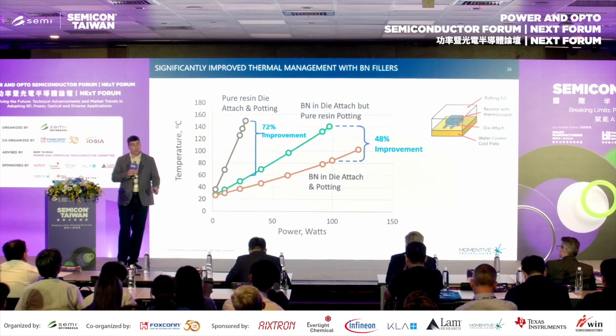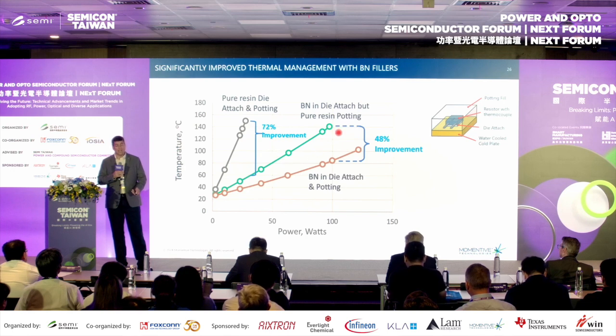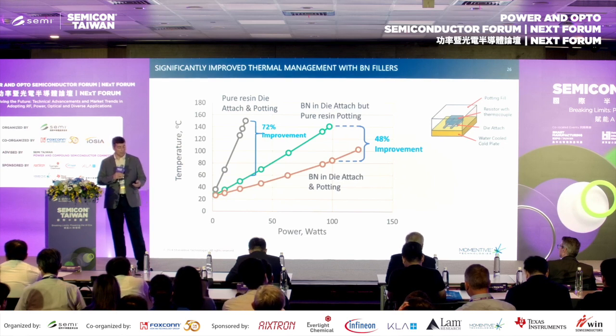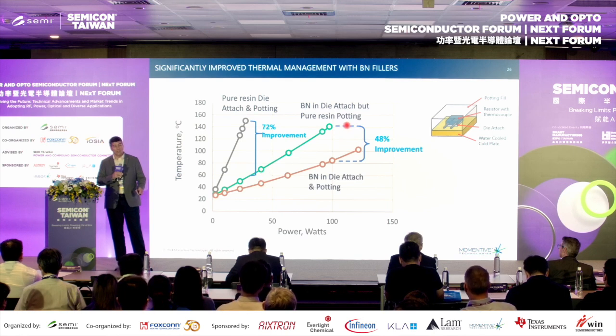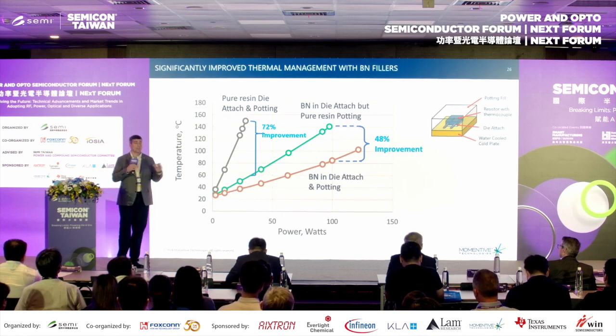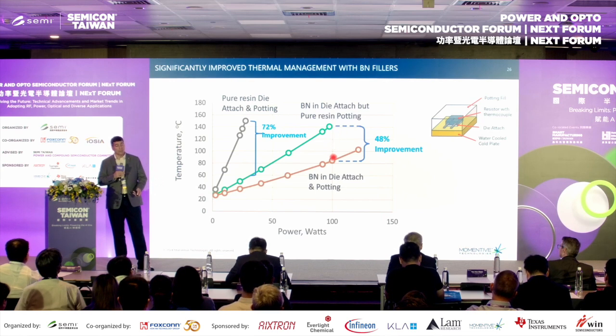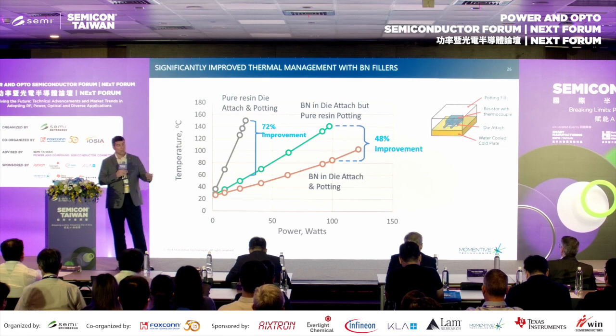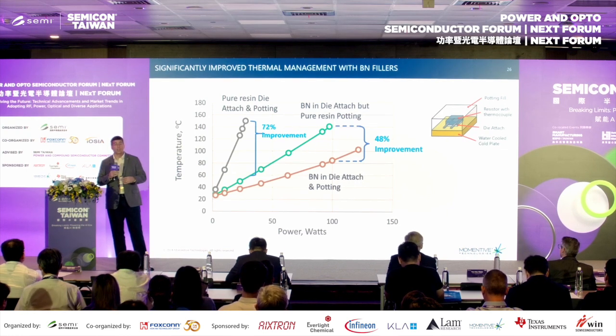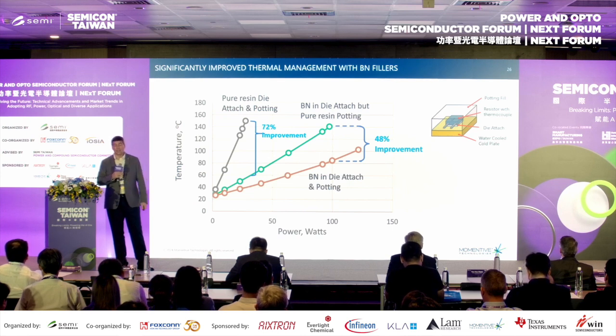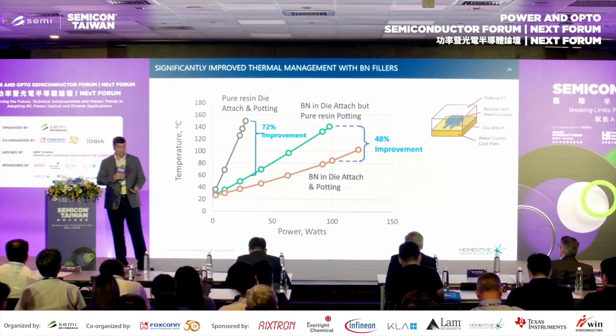Now if we put in 40 weight percent BN just into the die attach, so this is keeping a pure resin potting resin, but just putting 40% BN into the die attach, you get about a 72% improvement, right? You're down here at about 60 degrees at the same wattage. It follows this line. If you then go one step further and add the BN to the potting resin as well, you can get the drop that's shown here, which is about another 40%, 50% reduction in temperature by adding BN to that also, right? So again, it just goes to what are you trying to do, what are you trying to achieve, that you can, again, get heat out of the system faster. Again, particularly important around our power applications.